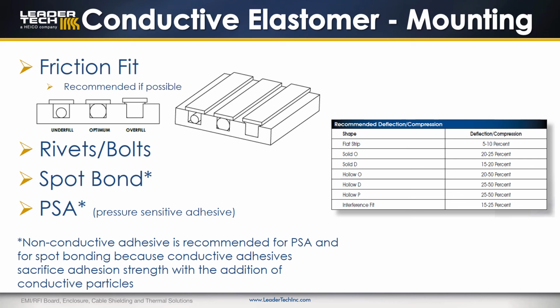Rivets, bolts, spot bonding, and PSA are other ways to mount. Non-conductive adhesive is recommended for PSA and for spot bonding because conductive adhesives sacrifice adhesion strength with the addition of conductive particles.